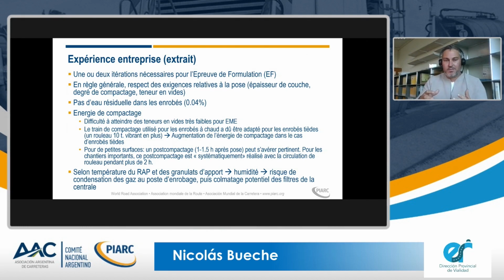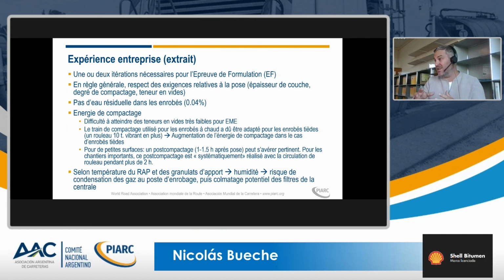It's a very simple measurement, but when we do it, we have to control the water content of the asphalt mixture at the job site. If you have too much water, then you will have problems. Here we got like 0.04%. It was okay. The foaming process was okay.